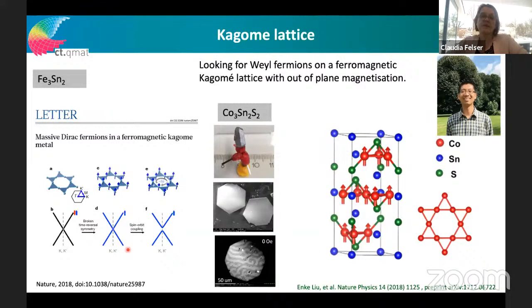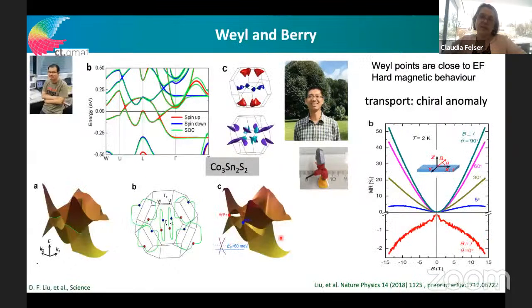Anyway, we thought we like our cobalt, and cobalt-3 tin-2 sulfide-2 is even nicer because this compound shows out-of-plane magnetization, and therefore it's hard magnetic. I told you we couldn't really see the Weyl points in cobalt-2 manganese gallium because it's a soft magnetic material, so we cannot apply a magnetic field in an ARPES machine. So we thought, oh, let's do this compound. We could grow very nice single crystals, also nice shiny crystals, which were a very nice starting point. So we looked at the electronic structure, and this compound has quite a simple electronic structure. It's more or less exactly what you want to have in the ideal case.